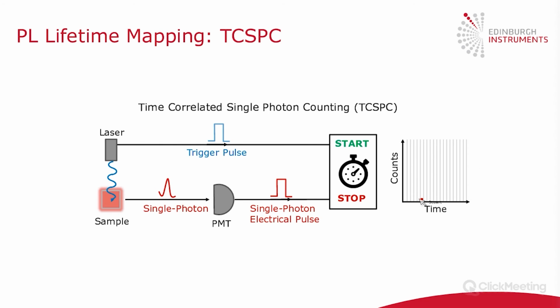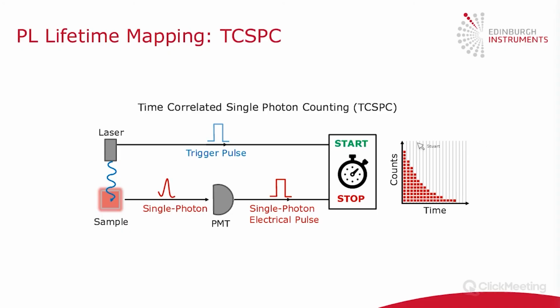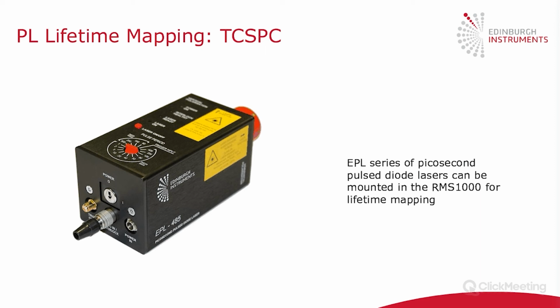If you measure once, you get a single point on this histogram corresponding to a certain time it took for this photon to be emitted. You then fire the laser again. Another point is added to the histogram. And eventually you build up the entire photoluminescence decay using this technique in order to get the photoluminescence lifetime out of the sample. So the RMS 1000 can do confocal photoluminescence lifetime imaging. Our Edinburgh Instruments picosecond pulse diode lasers can be mounted into the RMS 1000. This is a pulsed light source, and that's used to do the lifetime mapping.